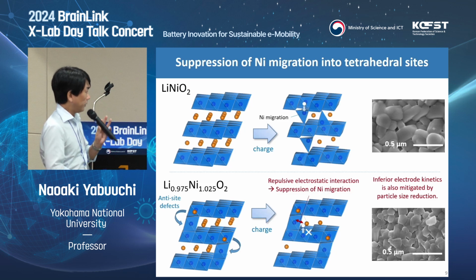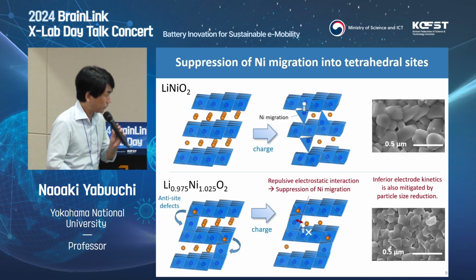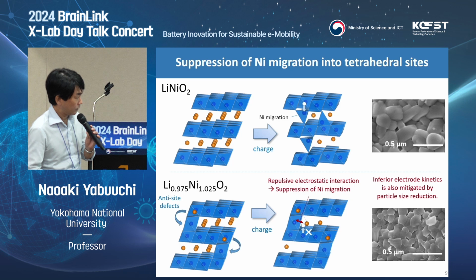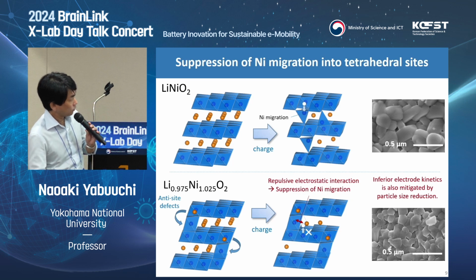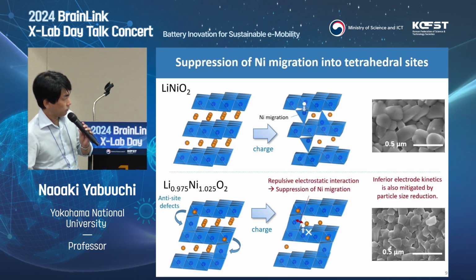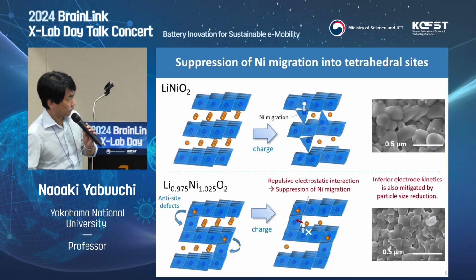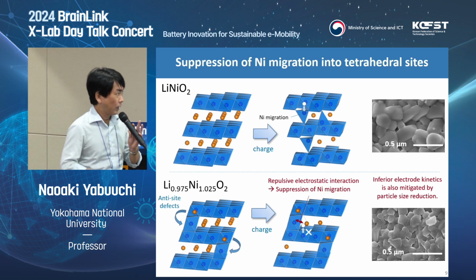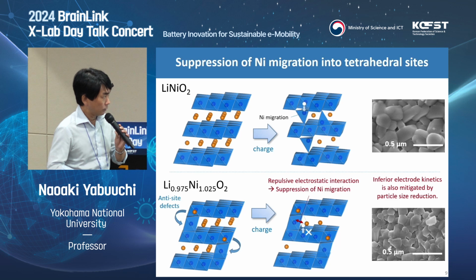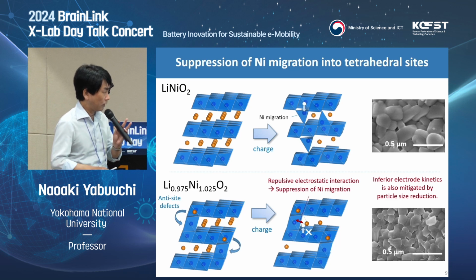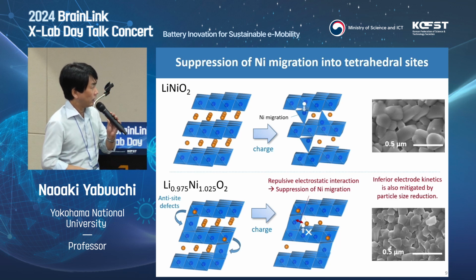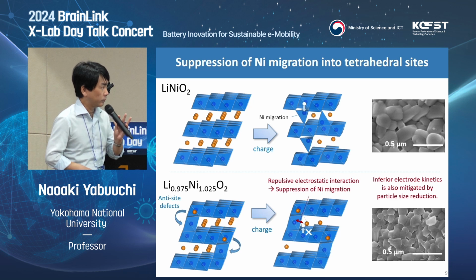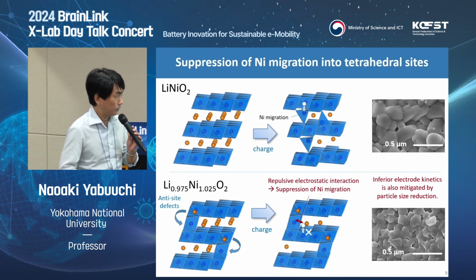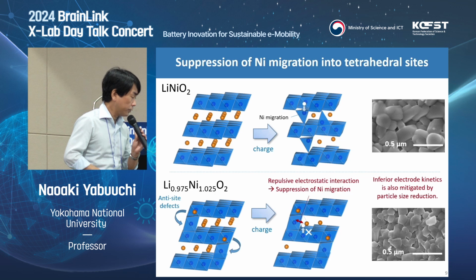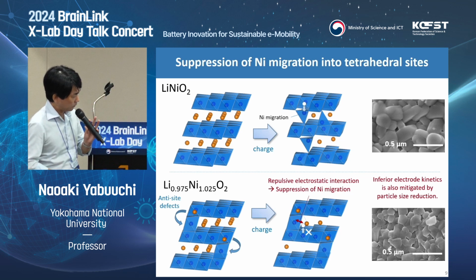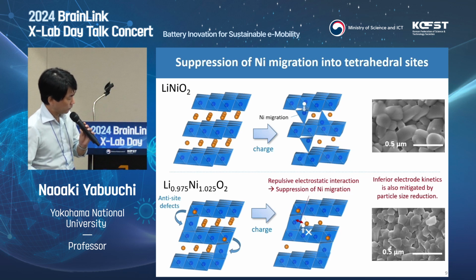So this is a summary of our hypothesis for the improvement by anti-site defects. In stoichiometric lithium nickel oxide, after lithium removal, nickel ions migrate to tetrahedral sites. After that, the under-coordinated oxygen is very chemically unstable. Therefore, it easily reacts with the electrolyte solution, leading to high impedance upon cycling.